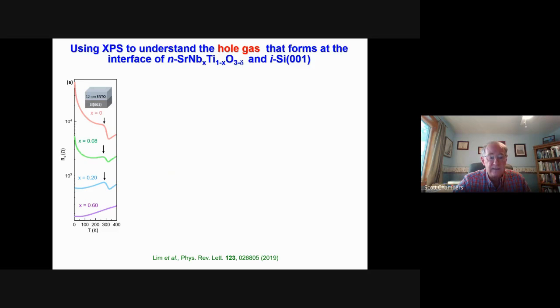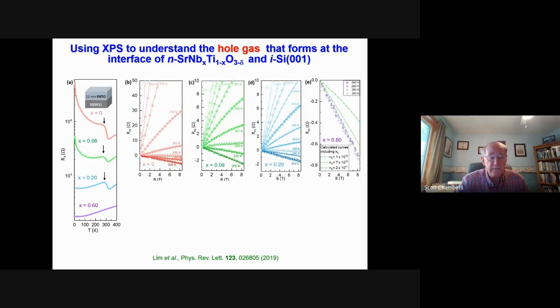But when we grew these films, in collaboration with Professor Joe Ngai at the University of Texas at Arlington, if you take a look at the sheet resistance versus temperature for different mole fractions of niobium, you get a really weird result, and that is this precipitous drop right around room temperature. If you then do Hall measurements to measure the transport, you find that as you go from below room temperature to above room temperature, the Hall coefficient goes from negative to positive, which indicates that the dominant carrier is going from electrons to holes. So below room temperature, the dominant carrier is electrons in the SNTO, and above room temperature, it's holes.